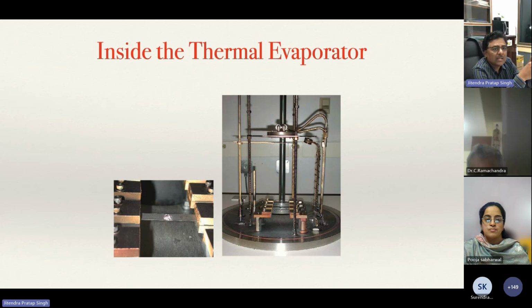So what happens is, when you deposit the material, equilibrium is never achieved because of the temperature, so there will always be some thermal stress at the interface. Because of that, the more and more material you keep depositing, the thermal stress will be such that the material will start peeling off.